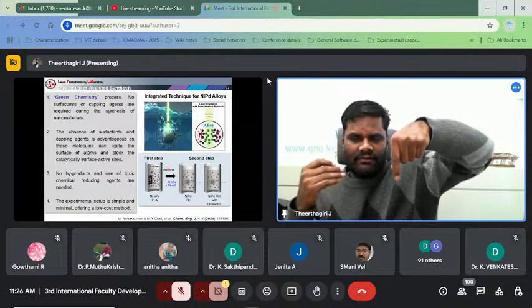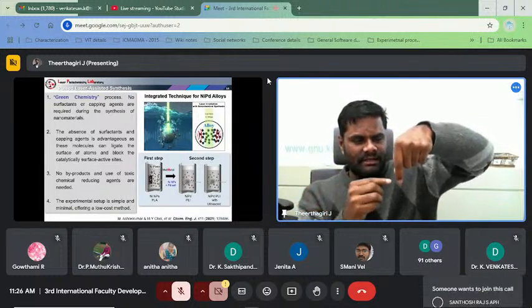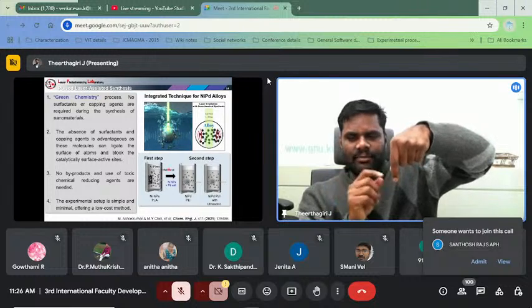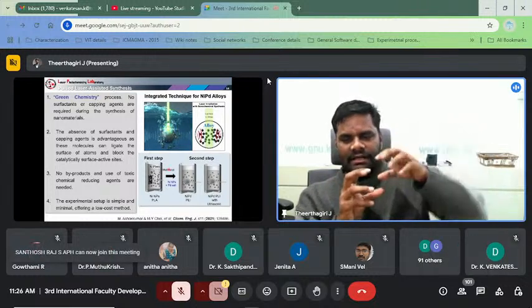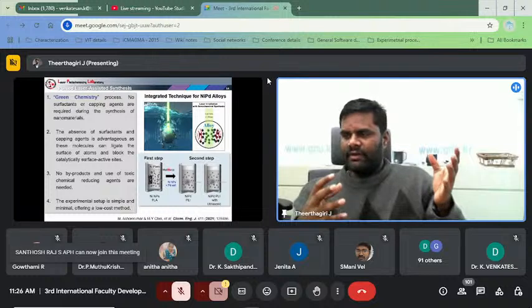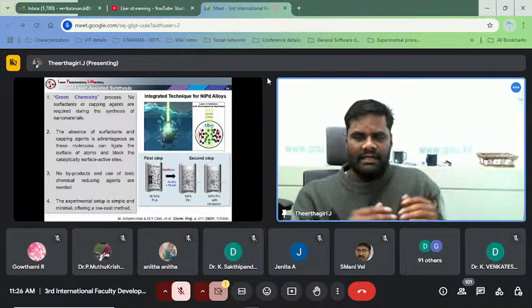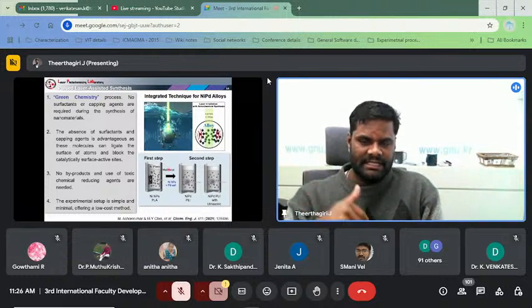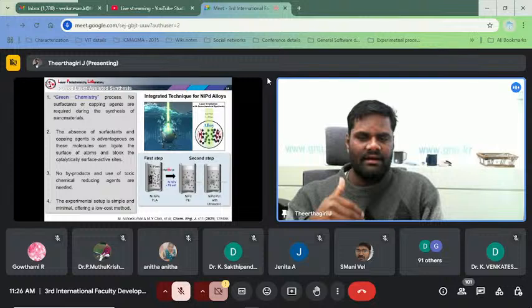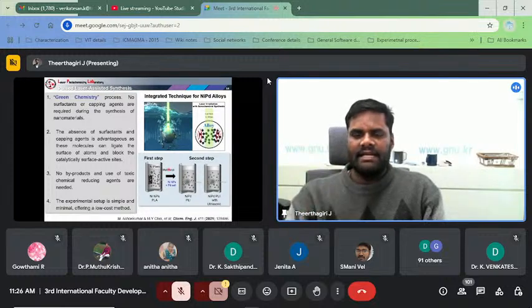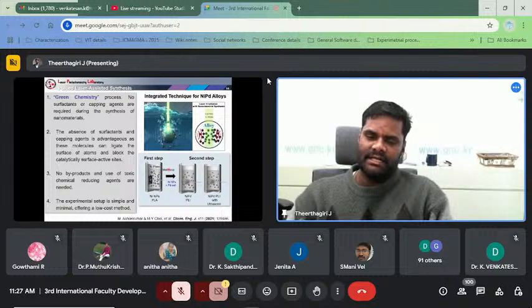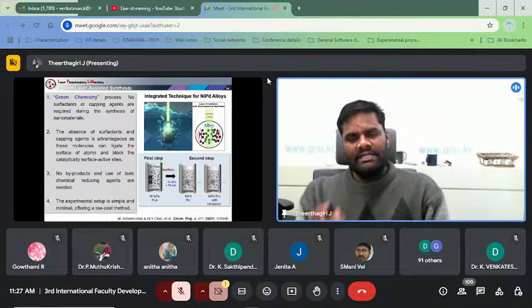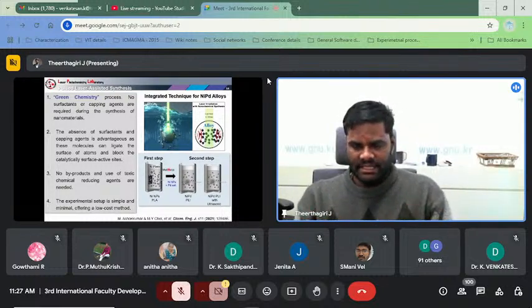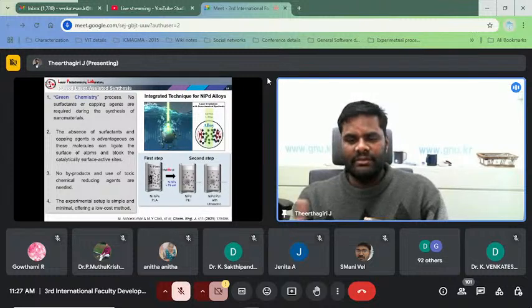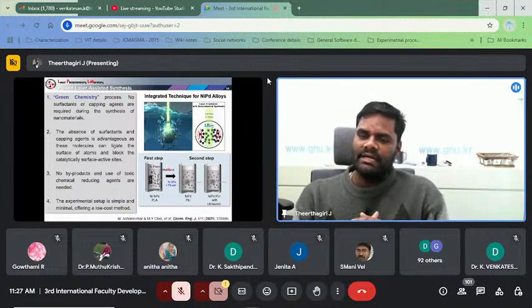How does this react? During the laser process, the solvent gets decomposed. For example, in the case of water, it can decompose into hydrogen and hydroxyl radical. The hydrogen radical acts as a reducing agent, while the hydroxyl radical acts as an oxidizing agent. It can lead to the formation of oxide material when I'm using water.